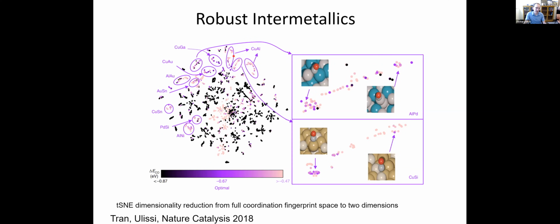So this is best case scenario for talking to an experimental collaborator. It's, look, copper aluminum is interesting. No matter what you do, it might be even more active. So that was at the top of the list. Quite a few of these other binary combinations, copper gallium, copper tin, aluminum nickel, also looked quite interesting. All of these ones in purple were the ones that we highlighted as potentially exciting and worth following up on.